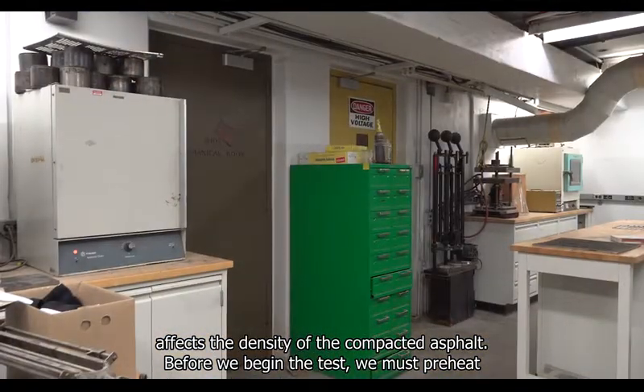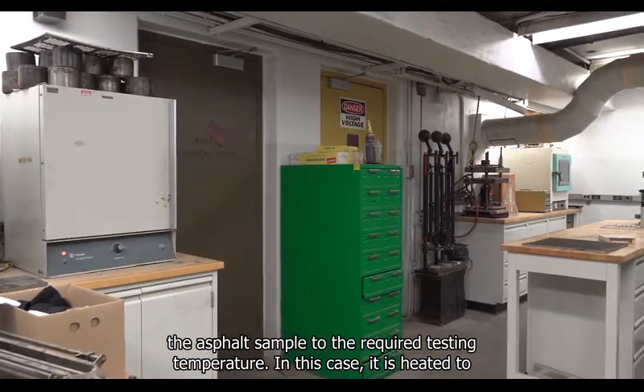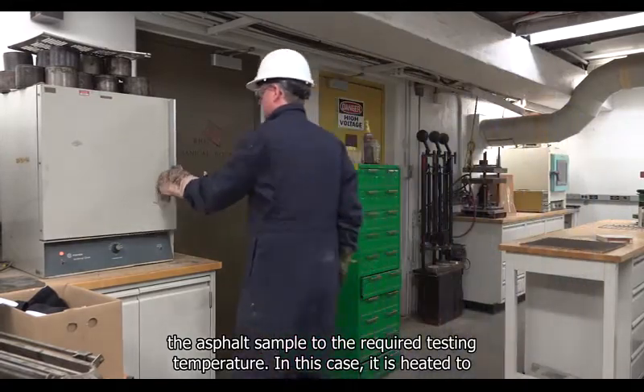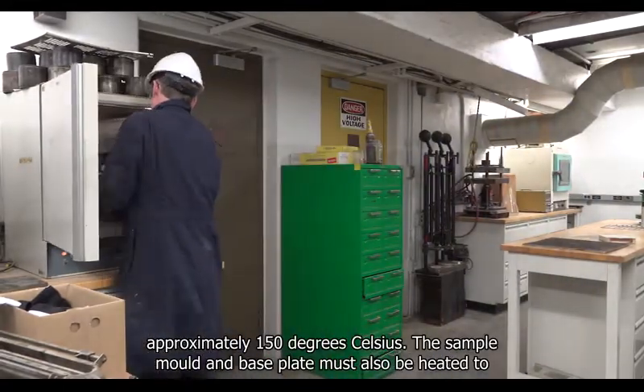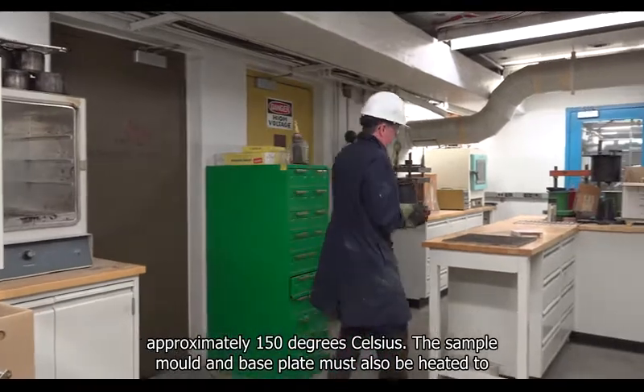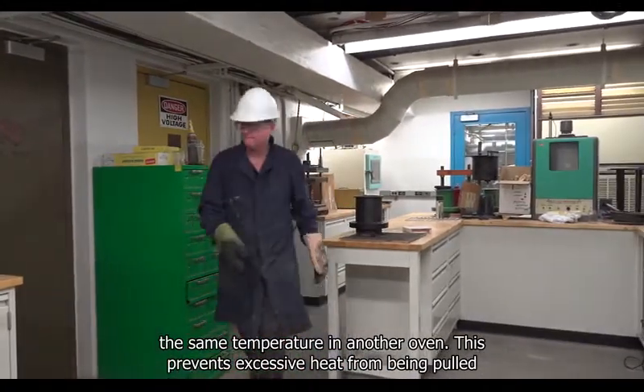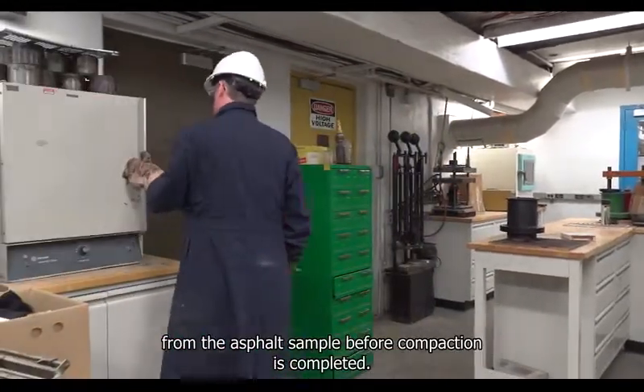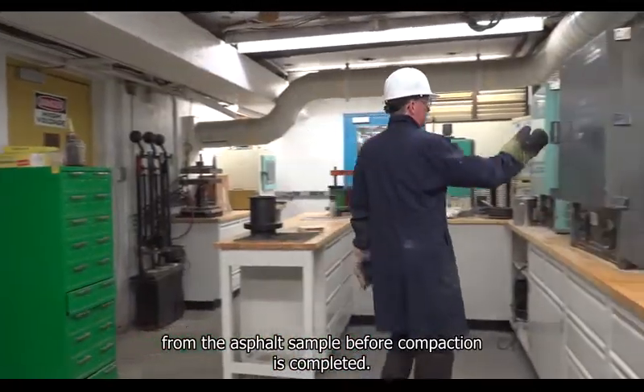Before we begin the test, we must preheat the asphalt sample to the required testing temperature. In this case, it is heated to approximately 150 degrees Celsius. The sample mold and base plate must also be heated to the same temperature in another oven. This prevents excessive heat from being pulled from the asphalt sample before compaction is completed.